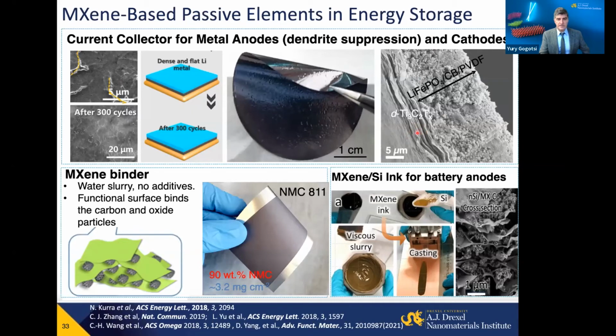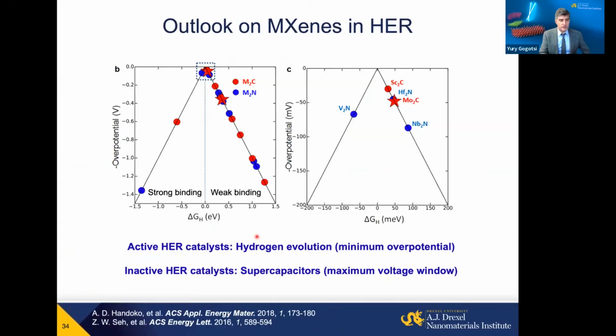And last but not least, they can be used in many current devices as passive elements. For example, the copper current collector in a lithium-ion battery takes about 17% of weight. If we can replace it by a 3 micron MXene instead of a 12 micron thick copper, which will be about 10 times lighter current collector, we can actually decrease the weight of the current battery and actually size because of thinner current collectors. We can use them as conducting binders that allow printing from water.